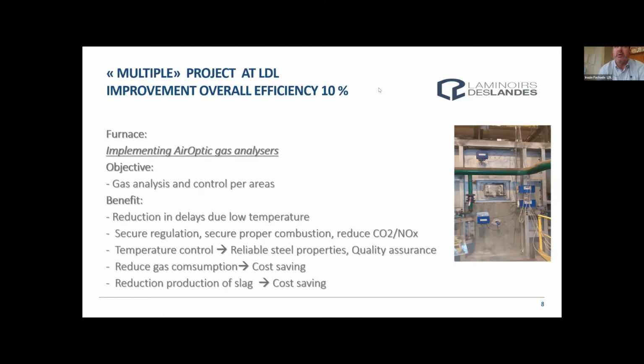Sometimes when we start the rolling at the beginning of the shift, despite the system telling us that we have the temperature, we start the first slab and we see when we start rolling that it didn't reach the proper temperature. So that will allow us to reduce these delays at the beginning of the shift. This gas analyzer will also allow us to secure the regulation of the furnace, secure the combustion, and reduce the CO2 and NOx.